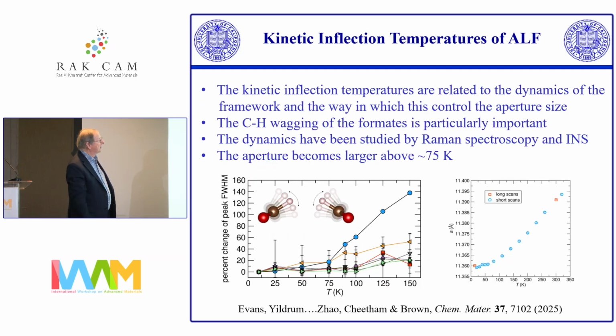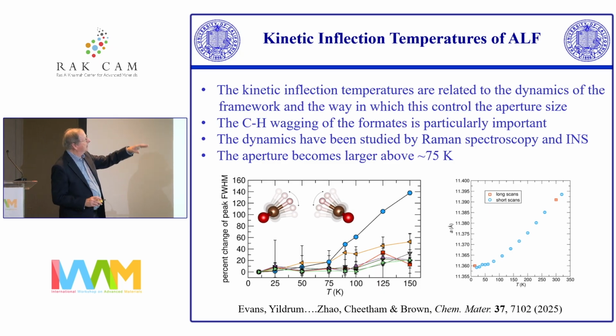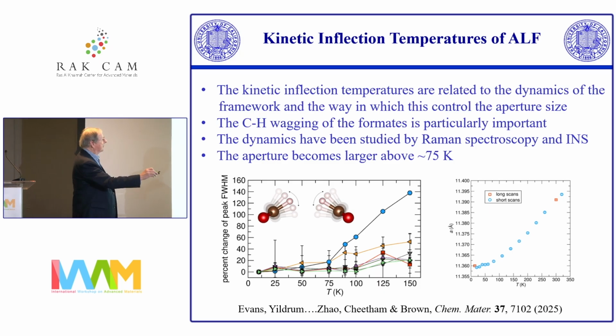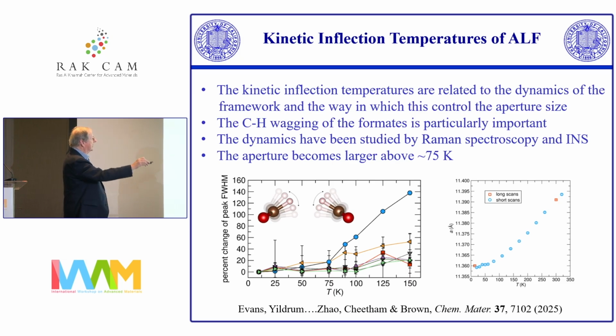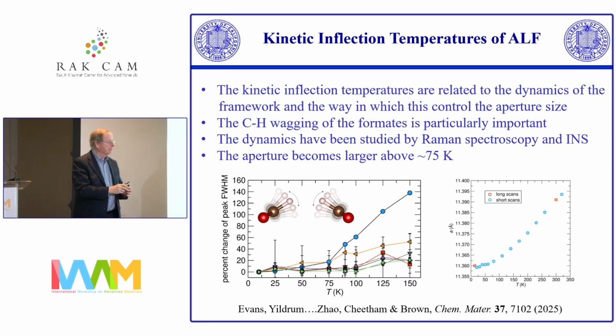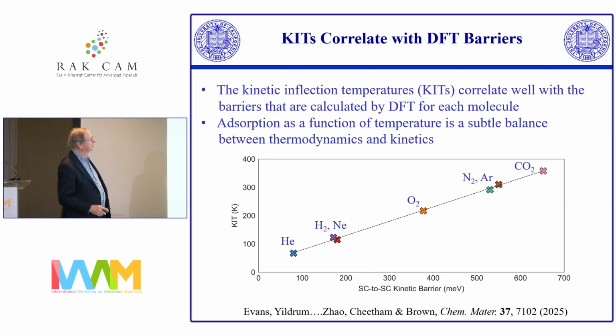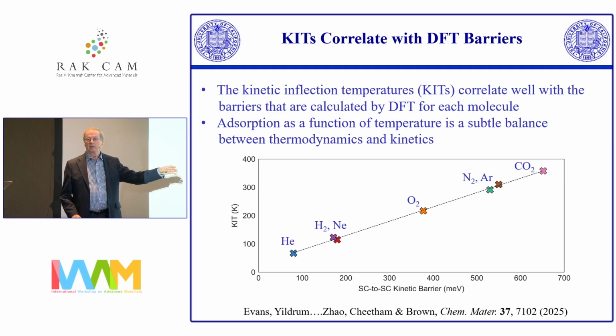So in the case of this, we've done lots of vibrational spectroscopy, Raman, inelastic neutron scattering, and this, for example, is the dynamics, the blue lines are dynamics of the sort of wagging of the hydrogens. And we've done molecular dynamic simulations on this. So the system opens up with temperature, and as you go further up in temperature, other things will be adsorbed. And we can calculate the activation energies.